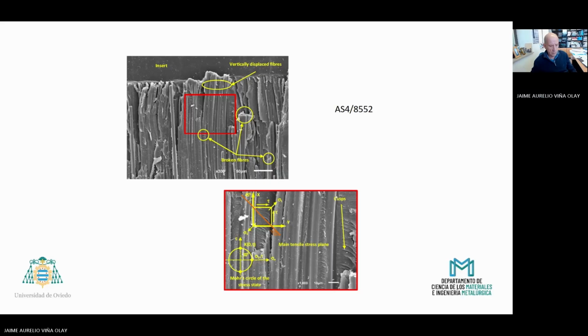Also, for ease of interpretation, the stress state generated at the point in this fracture region has been generated in this figure for a reference system XY, where the x-axis is located along the longitudinal direction of the specimen. This stress state is dominated by tangential stresses, you can observe here the tangential stresses in the direction of this reference axis. The main tensile stress generated in the specimen, obtained by means of Mohr's circle, are likewise represented in the figure. The orientation of these stresses is shown, as well as the plane in which they operate, which basically coincides with the observed fracture planes.